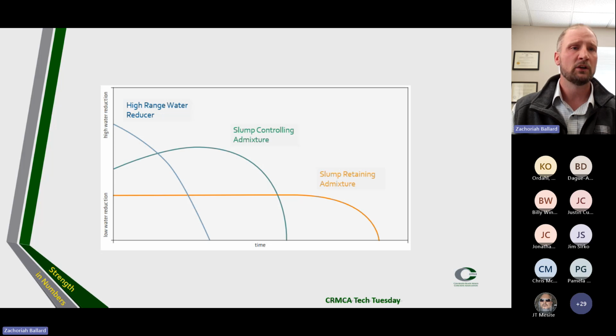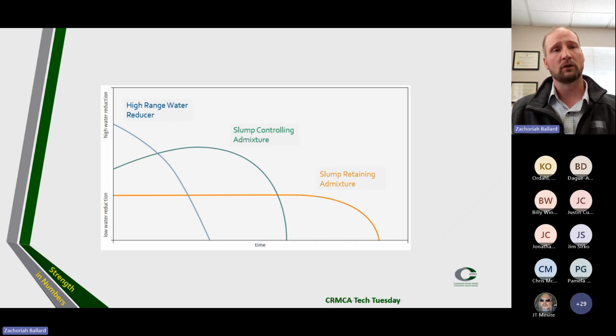We have some charts generally by admixture suppliers that show if we have a high range water reducer that's on the left, we get a larger amount of water reduction, but the time that slump stays is not as long. We have some slump controlling admixtures and slump retaining admixtures, but those are generally not going to give us the same high water reduction values. So as we push admixture dosage higher and higher and reducing our water lower and lower, we're going to start to run into some problems.